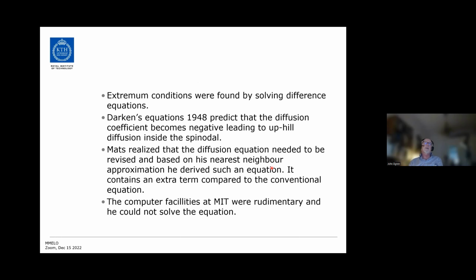Mats had to look at extremum conditions by solving difference equations, which was tedious. Darken's equation showed that the diffusivity inside the spinodal would turn negative and lead to uphill diffusion. And then Mats realized that the diffusion equation needed to be revised.